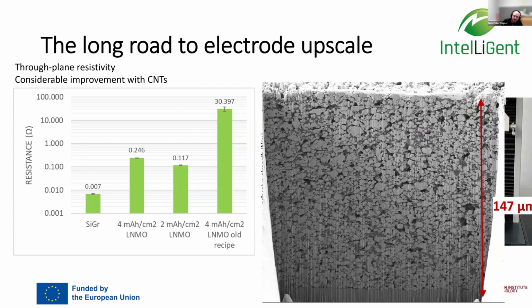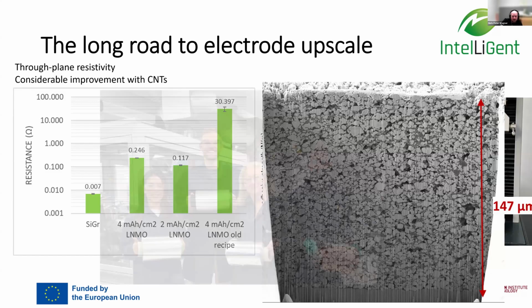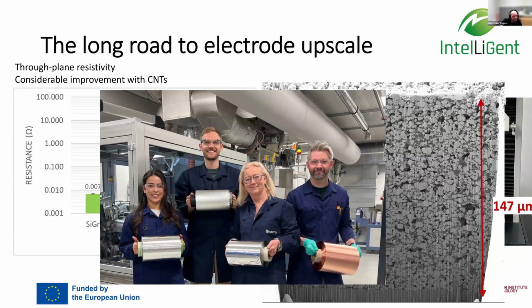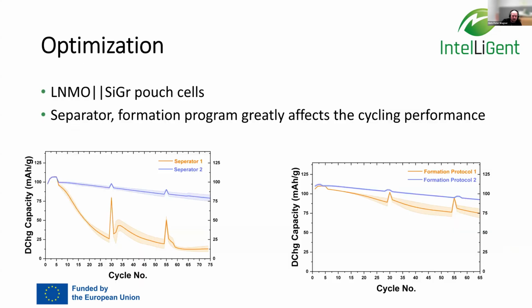So here is an example of what our electrodes look like in cross section. They're nice and homogeneous. They were calendered to about 2.4 grams per cubic centimeter, and based on a single crystalline LNMO material. My proud colleagues made over 100 meters of electrodes, and of course we didn't want to waste these 100 meters, so we did a lot of tests initially on how to optimize the separators that we put into these cells, and also how to optimize the formation protocols to really get the best out of our electrodes. And that was a big success.